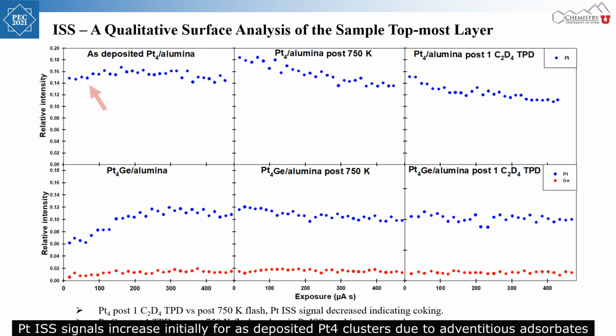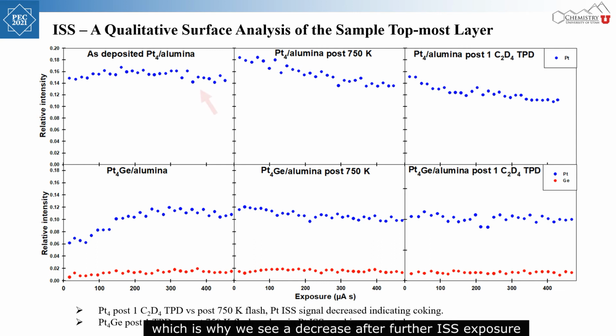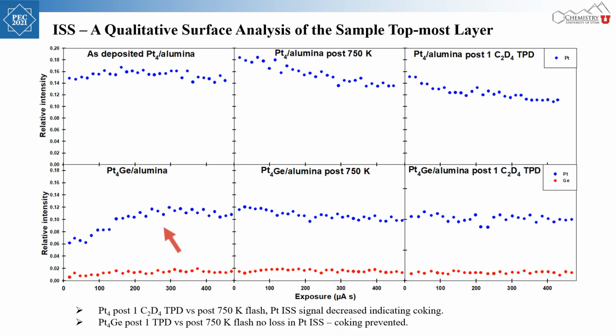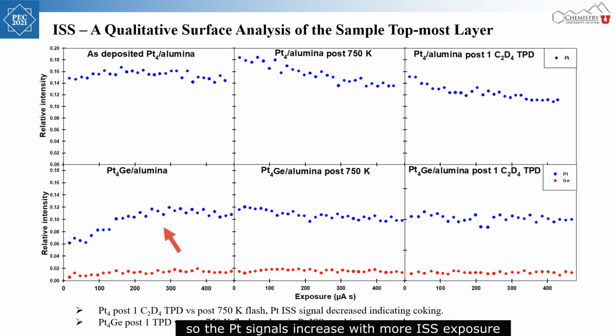Platinum ISS signals increase initially for as-deposited platinum-4 clusters due to adventitious adsorbates. The adsorbates are sputtered away by the helium beam, so more platinum atoms are exposed. The helium beam continues to sputter the sample and will start destroying the platinum atoms, which is why we see a decrease after further ISS exposure. Similarly, platinum-4 germanium clusters are covered by hydrogen and chlorine atoms, which are slowly removed by the beam sputtering, so the platinum signals increase with more ISS exposure.